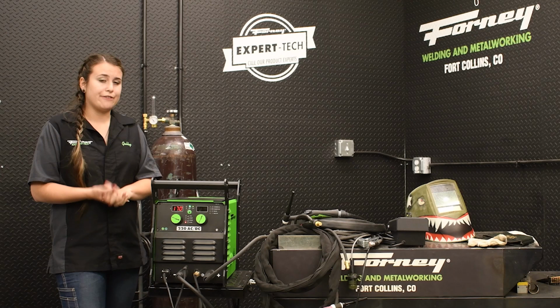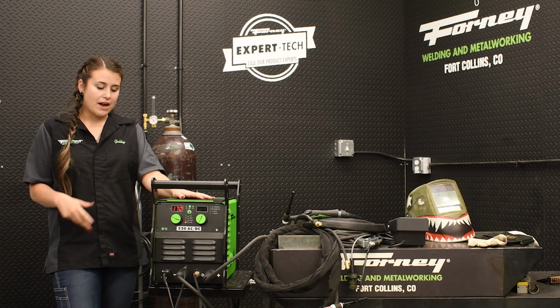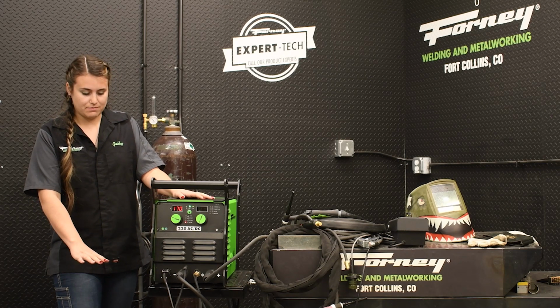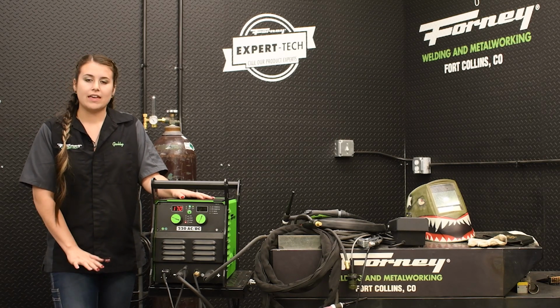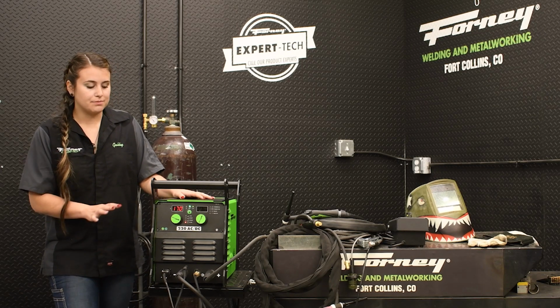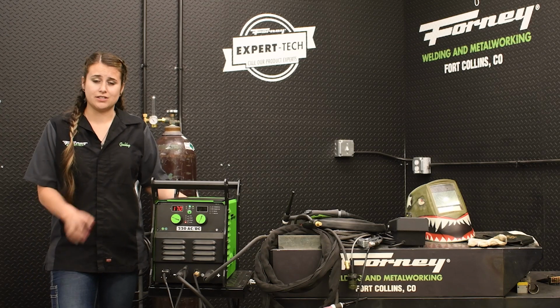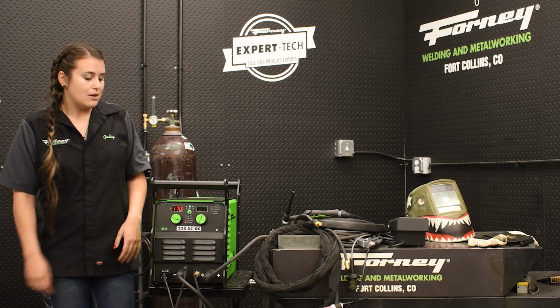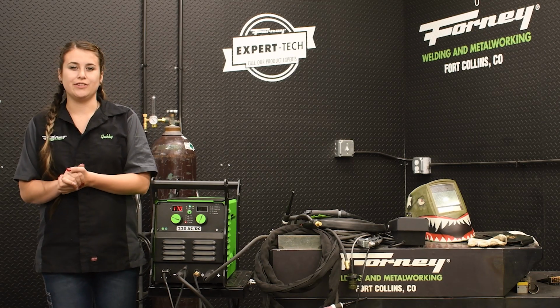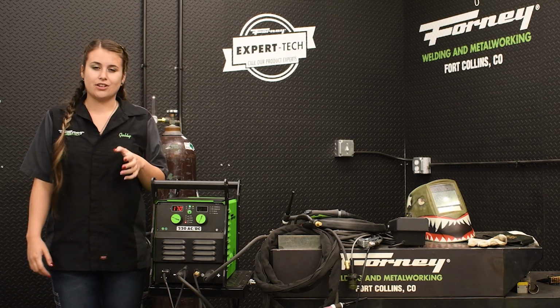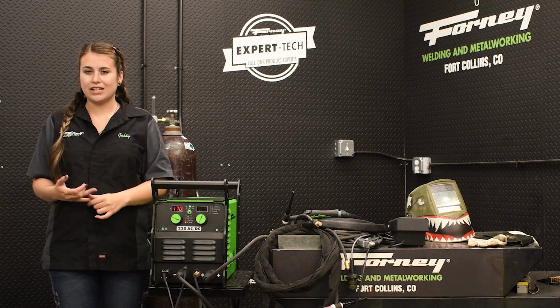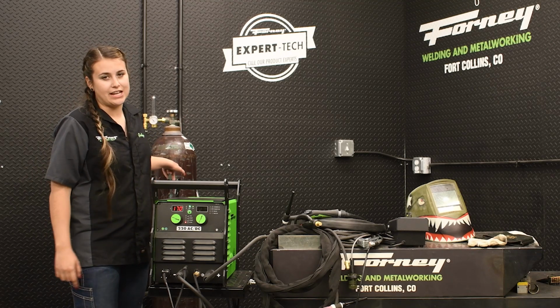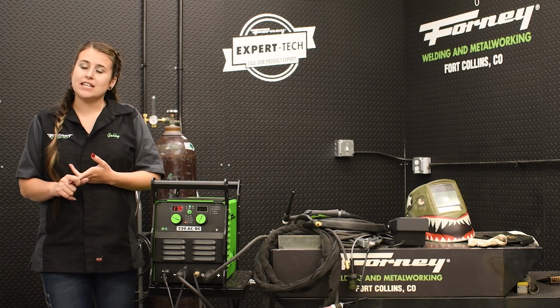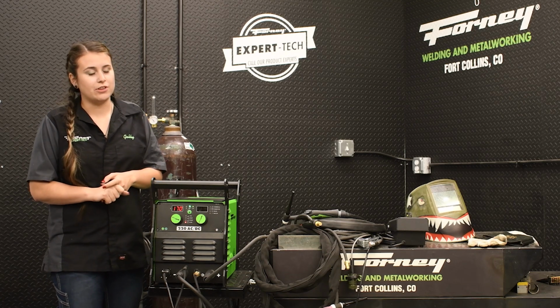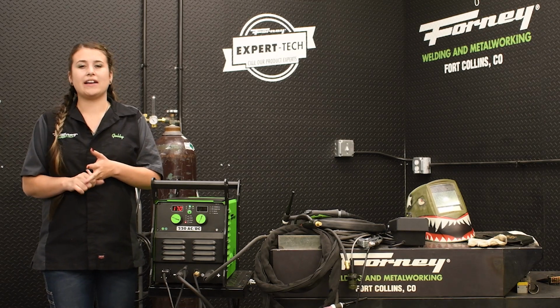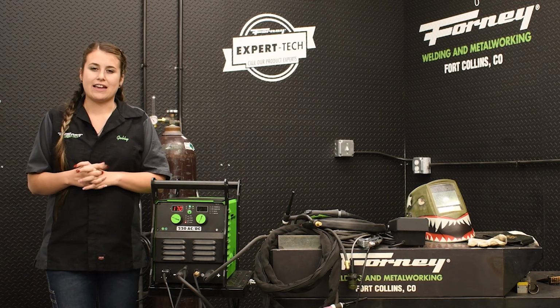Another good thing to keep in mind is that if you're welding right next to this machine, if you have your plate on a piece of metal or table or whatever next to your machine, and you see impurities, it is more than likely because the fans on the back of this machine are so powerful that it's going to be pushing air out of these louvers, which will cause the gas to be blown away from your torch. So make sure that if you're seeing impurities or it's looking like you're not getting gas coverage, one, your bottle's full and you actually have gas, two, you're set between 15 and 20 CFH on your flow meter, and that you have no external air blowing to allow that gas to be blown away.